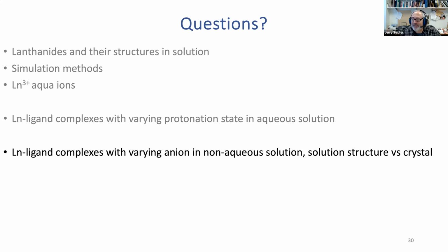Matt Newell, you have a follow-up? Yeah, I do. This is exactly a follow-up to Fair's point. If you could do those fits, the RDFs you showed look pretty peak-like, maybe slightly skewed, but fairly peak-like. And then from that, you would get fitted RDFs, and you could use that directly with the MD structures.